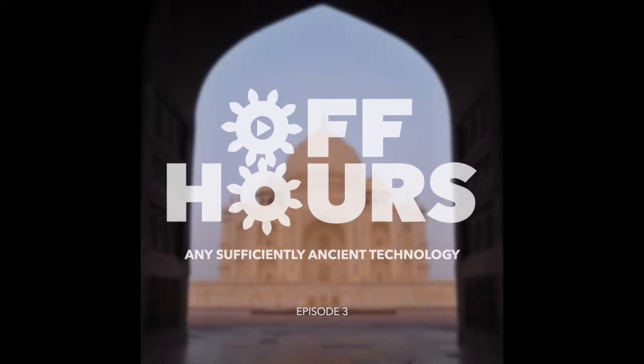In my case, I use a vacuum caster, and when you start getting into industrial level casting, places like, let's say, Rio Grande, who are casting their own findings and whatnot, they're using large vacuum casting setups. And there are a lot of advantages to vacuum casting setups, primarily in that you can get very, very fine detail and fill those molds easily on a much larger scale flask. If you imagine with a centrifugal casting setup or a sling casting setup, if you have a very large flask, you then have a lot of mass and a lot of inertia flying around, which then becomes dangerous to deal with. In the case of vacuum casting, you don't have anything flying around.